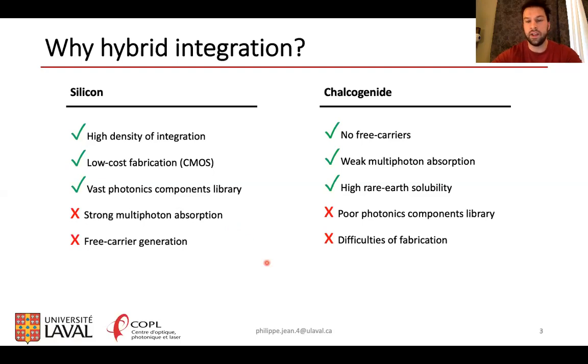In contrast, chalcogenide is a highly nonlinear material that doesn't suffer from free carriers and also has weak to negligible multiphoton absorption. It also has the perks of being rare-earth soluble and transparent in the mid-infrared. But chalcogenide photonics doesn't have a very well-developed photonics component library, and it's also difficult to fabricate because chalcogenide is pretty brittle. So the goal of a hybrid integration method would be to combine the strength of chalcogenide with silicon in order to overcome the drawbacks of silicon photonics while retaining the strength of the platform.